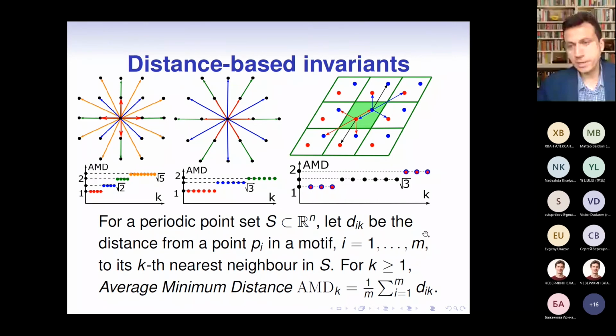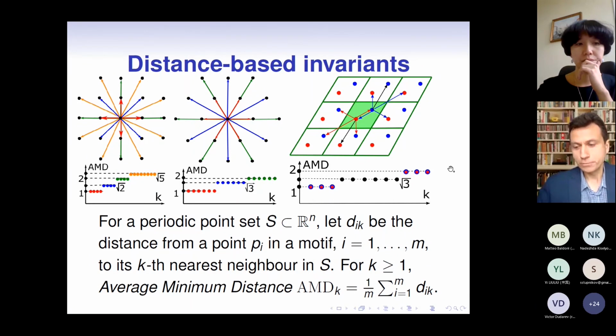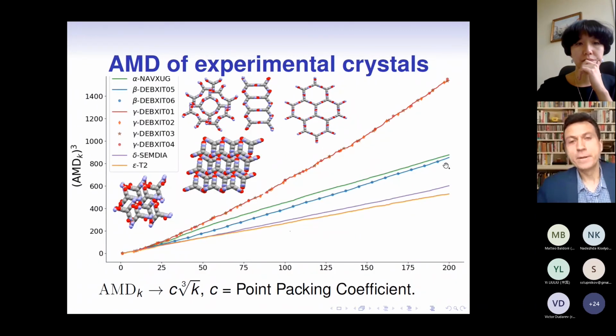But today I focus on the simpler AMD because the average minimum distance is a vector of numbers. So it's AMD1, AMD2, and so on, up to a given number k of neighbors. And this number k is a parameter. However, when we increase k, we don't change any previous values of the AMD invariant. So this k can be considered as an order of approximation, or the number of decimal places on your calculator. So you could compute up to 2 decimal places or up to 100. So you simply make better predictions.